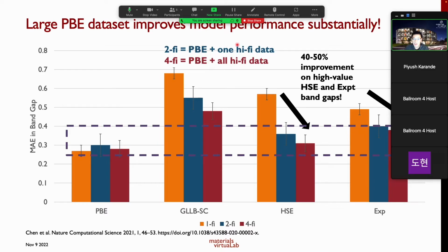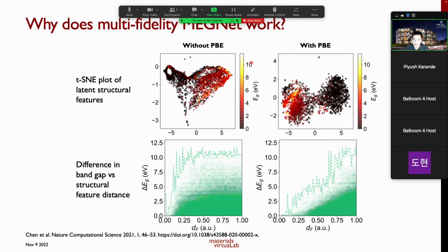For example, by just combining the PBE data with one of the high-fidelity data sets, like HSE, we can already reduce the mean absolute error in the prediction of the band gaps by about 40 to 50%, okay? Same for the experimental band gaps, right? Whenever I show this data, a lot of people wonder, how does this work? Because we are not increasing the amount of HSE or experimental data, but somehow we get much better performance on them. The reason is that even though the PBE data is relatively inaccurate, a large PBE data set significantly improves the latent structural features such that you have a good separation of high band gap and low band gap materials. And it is this improvement in the latent structural feature space that we believe is responsible for the improved performance on the HSE and experimental band gap data.